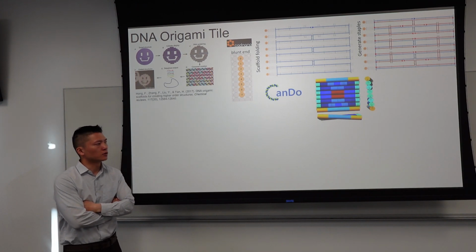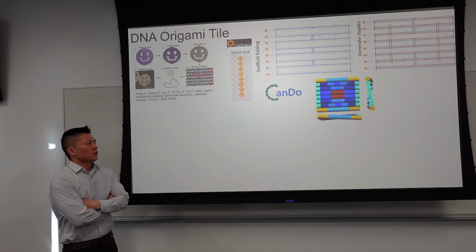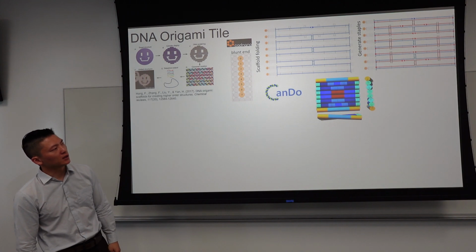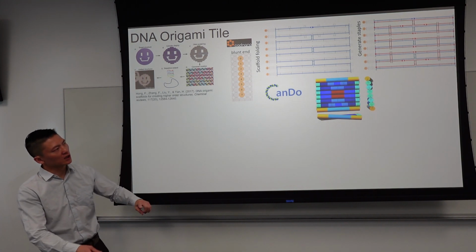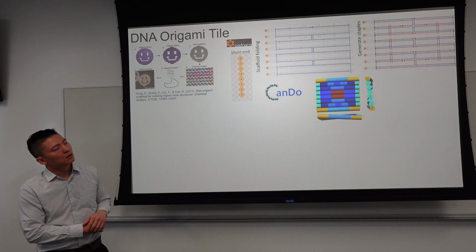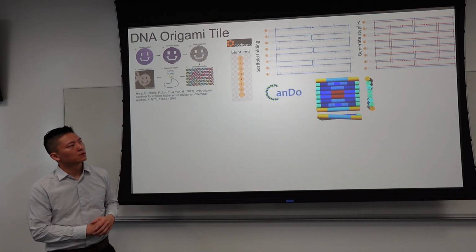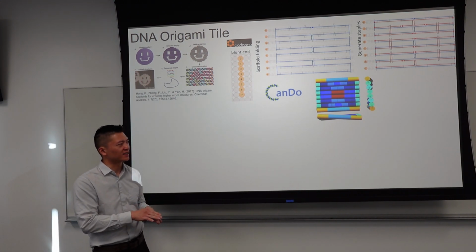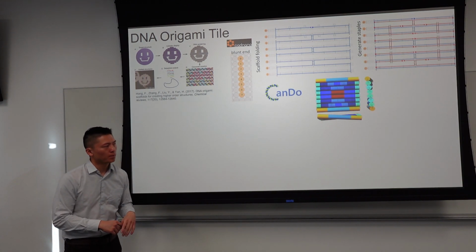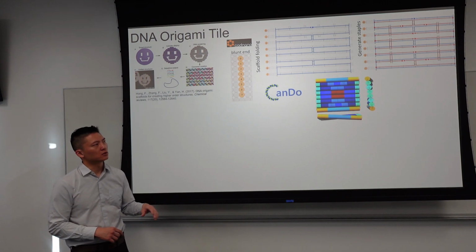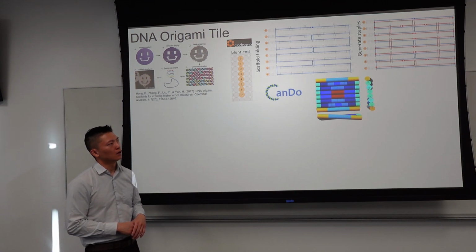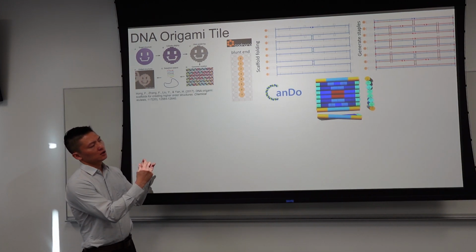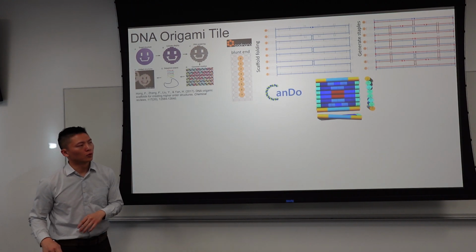Again, the rods are considered DNA helices. Yeah, so definitely we see some twisting happening here. Mainly it's because each time a crossover is formed, in order to bind the helices together, crossovers are needed, and those crossovers are not exactly at the correct positions maybe. And in addition, these Holliday junctions are holding DNA strands, negatively charged double-stranded DNAs together, and so we get these global twists,